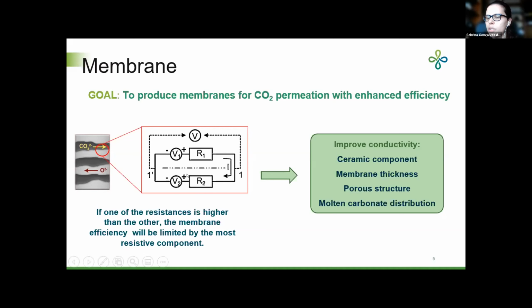If one of the resistances is higher than the other, the membrane efficiency will be limited by the most resistive component, that in this case is the ceramic phase. So have in mind that the permeation rate of the membrane is limited by the high resistance of the ceramic. To improve the efficiency of the membrane, we need to improve the conductivity.